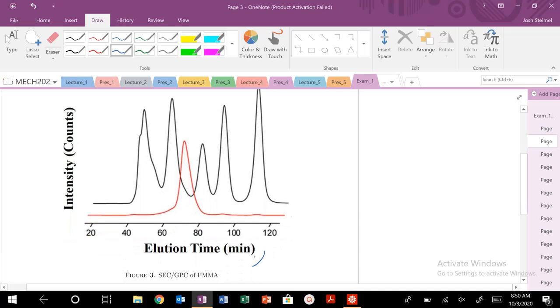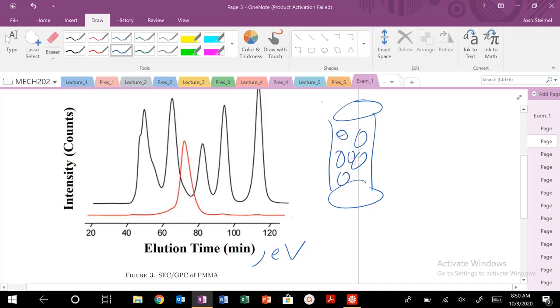So for my first set of experiments, I know that if I'm doing intensity versus elution time, or it could also be elution volume too. I know that for my size exclusion chromatography, in my column I have those beads, and the solution is flowed slowly through these. It's going to either interact with the beads, these pores, if they're small enough in size, because of the energy competition here. Mixing polymers want to go in the pores, but the conformation change or penalty does not want to enter the pore because you have to compress the polymer. So the polymers that are large are not going to want to explore any of the pores, regardless of this delta S of mixing. The energy penalty is too large. So low elution time, low elution volume, as we kind of saw in our lecture 7 notes, is going to be my time limit.